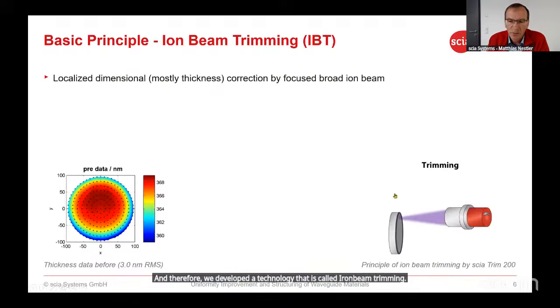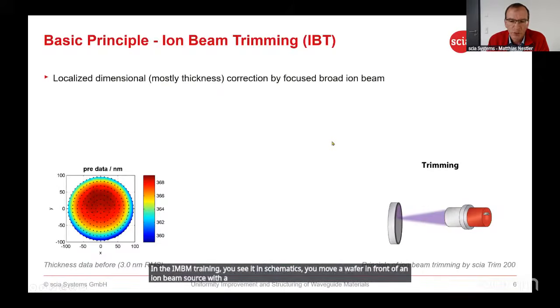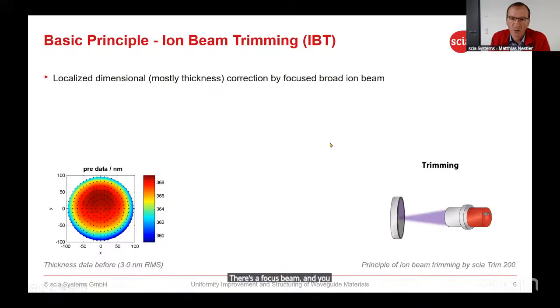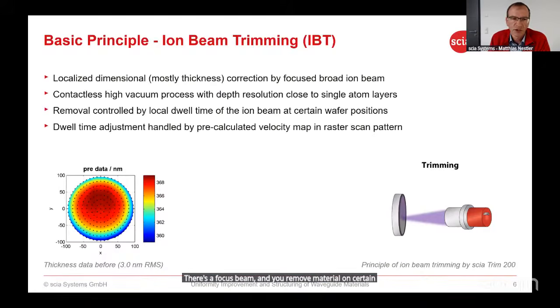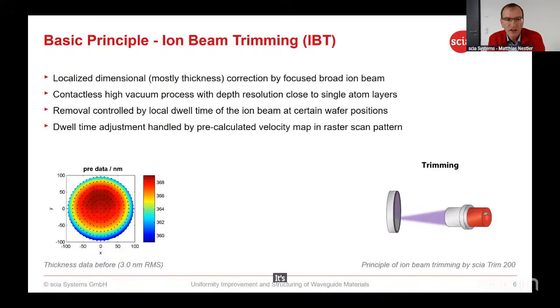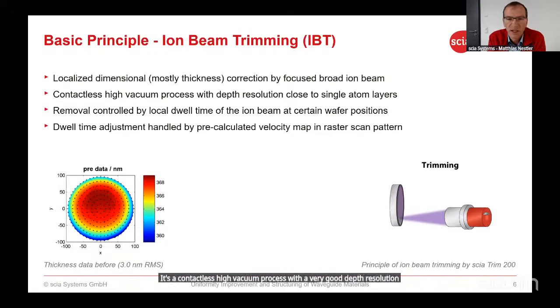In the ion beam trimming, you see it in the schematics. You move a wafer in front of an ion beam source, a broad beam ion source with a focus beam, and you remove material on certain positions. It's a contactless high vacuum process with a very good depth resolution, close to single atom layers.